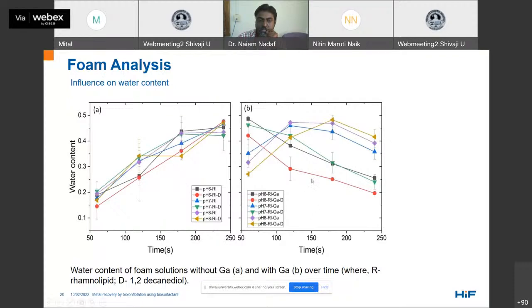Whereas the water content decreases in case of gallium, alone or with 1,2-decanediol. In some cases, it increases first and then decreases, but it decreases in the later stage. So here we can say that the presence of both gallium or gallium and decanediol results in faster drainage of foam, and that's why the water content is low. And we can relate these findings very well with the flotation results that I told you earlier. And we can see this already from the pictures.